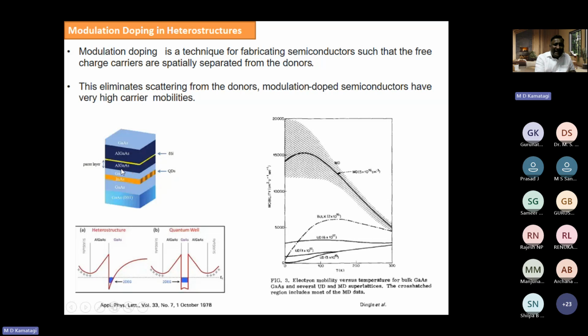This will act as a spacer, and on that another layer will be formed, this aluminum gallium arsenide, where we dope it. So modulation doping is a technique in a semiconductor such that the free charge carriers are spatially separated from their donors. Here the donors are there, and the electrons from these donors lose energy and come and sit in this junction. In the quantum well, the electrons want to sit in the lowest possible energy, and the lowest possible energy is somewhere here. They lose energy and come and sit and form a two-dimensional electron gas.